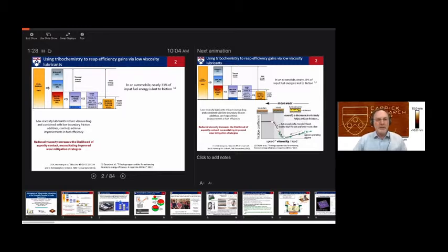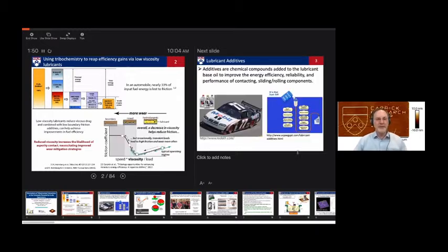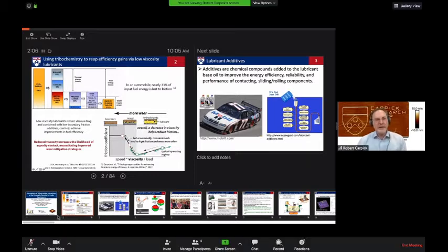One of the major thrusts in industry for some time now has been to try to enable the use of lower viscosity lubricants, because of course you'll reduce the viscous drag as the lubricant moves through the system, the churning losses that exist in the mechanism, including in car engines and in gearboxes. But of course the risk is this: as you move along the Stribeck curve here, if you lower the viscosity, of course you lower the friction, but you start getting boundary contact at points of contacting moving interfaces.